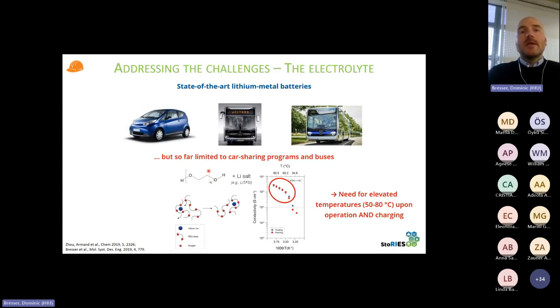The basis of the electrolyte in this case is polyethylene oxide, or abbreviated PEO. A very simple polymer, quite cheap. And then there's a lithium salt added, such as lithium TFSI. Apparently the commercial systems are a bit more complex, but it's basically based on these two components. And then you see here the conductivity as a function of temperature. You have reasonable conductivities around 10 to the minus 3 siemens per centimeter, around 60 to 90 degrees C, where the polymer is entering the liquid range. And then once it's getting solid, it's dropping to a level where it's not really useful anymore in commercial battery cells.